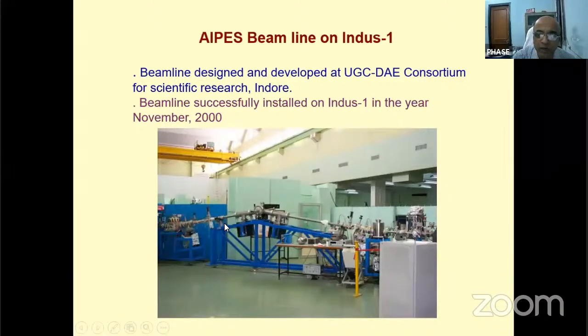All the chambers are connected by the pipeline, which is under ultra high vacuum. All these chambers are ultra high vacuum, and this complete pipeline is also ultra high vacuum. It is connected to the electron accelerator storage ring, and that storage ring is also under ultra high vacuum. So vacuum experts play a major role while running this experiment. If a small leak is there, your vacuum will go down, and the X-ray beam coming from Indus will also get lost. That's why vacuum is very important. You have to do the experiment in the order of 10^-9 to 10^-10 torr. That is the vacuum order inside this chamber.